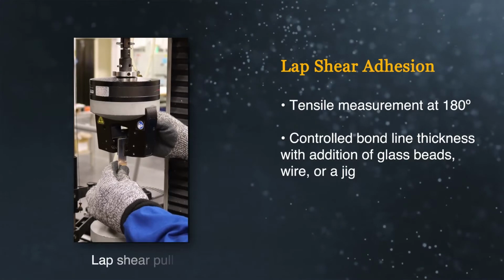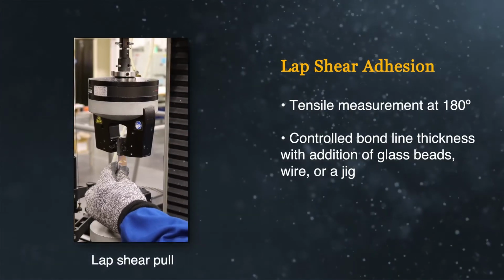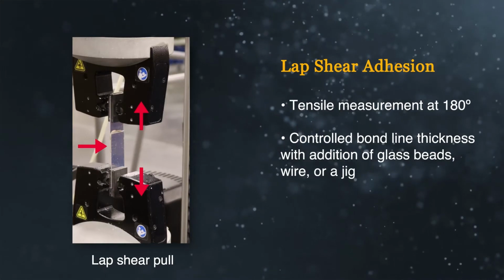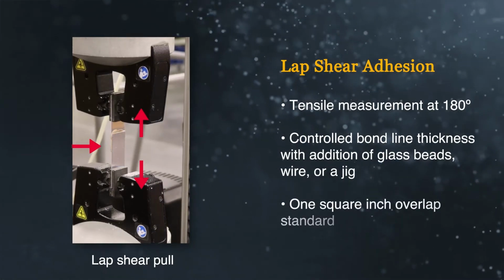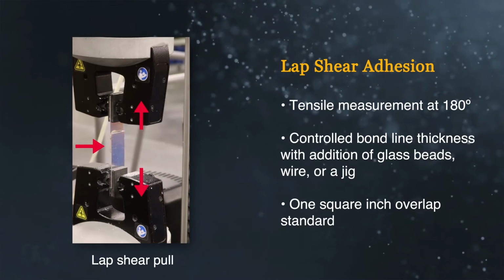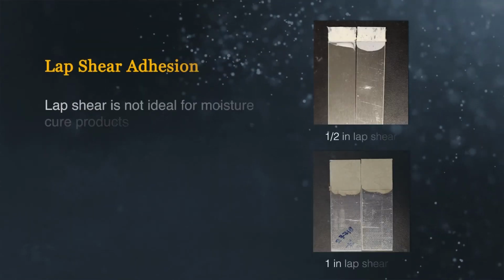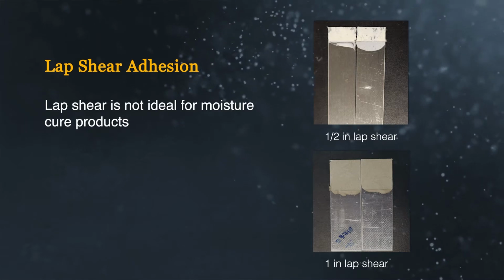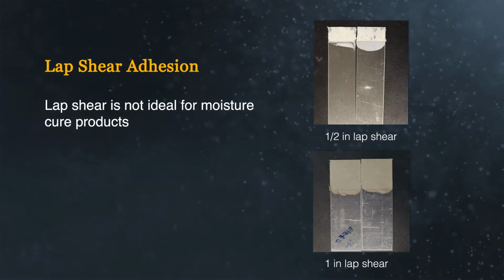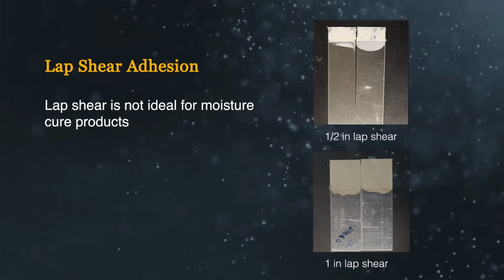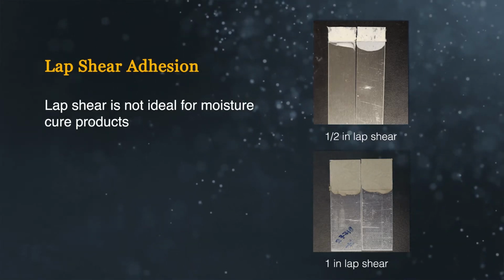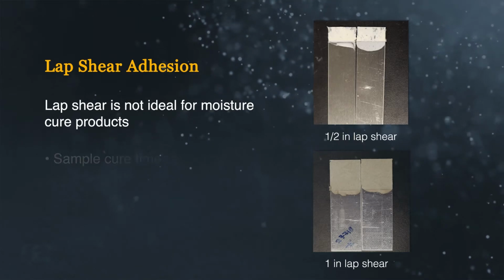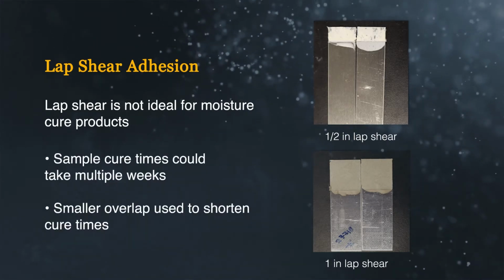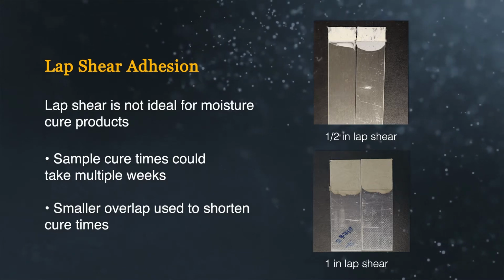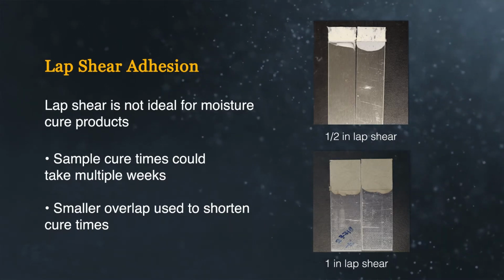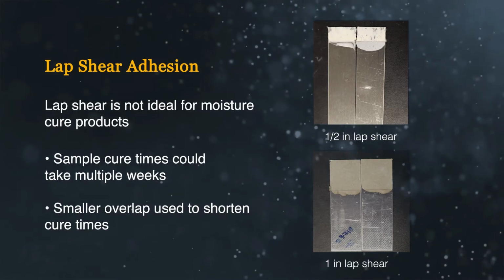The test consists of pulling the two substrates apart at 180 degrees and measuring the force required to pull them apart. Typically, the substrates overlap by 1 square inch. Since the material is confined between substrates in lap shear testing, it is not the most ideal method for testing moisture cure products. These products require moisture in the air to cure, and due to the confined overlap, curing rates will be much slower, sometimes taking weeks to cure a sample. To mitigate this, smaller overlap dimensions are used, with 1/2 inch overlap to cure samples in 1 week.